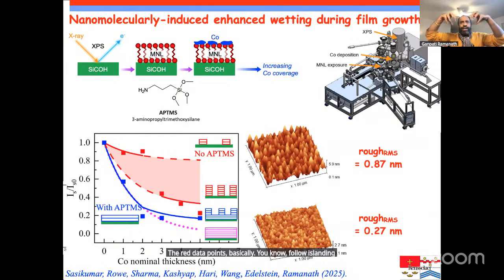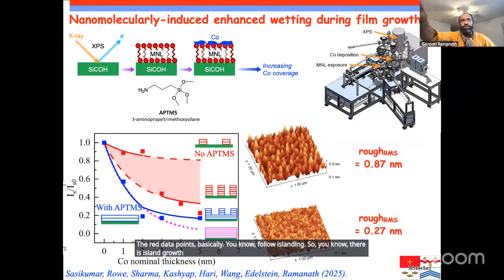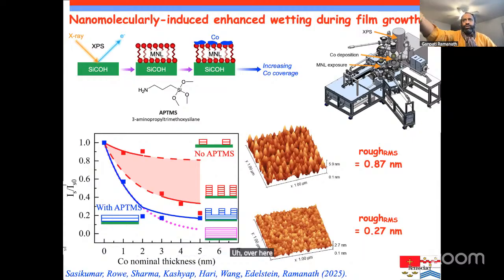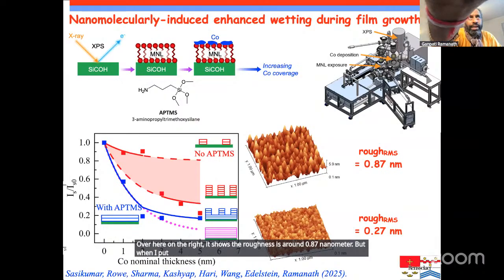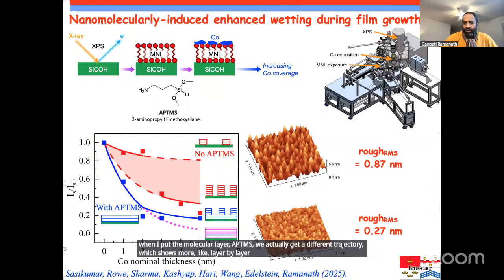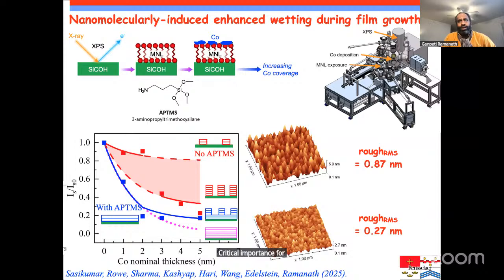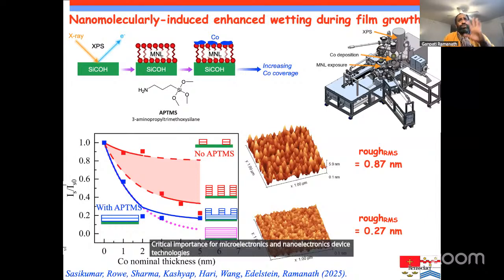So, there is island growth of these metals that is shown by atomic force microscopy on the top over here on the right, which shows the roughness is around 0.87 nanometer. But when I put the molecular layer, APTMS, we actually get a different trajectory, which shows more like layer by layer growth, which is actually giving us much smoother films. This is of critical importance for microelectronics and nanoelectronics device technologies. So this is the kind of things that we are playing with.